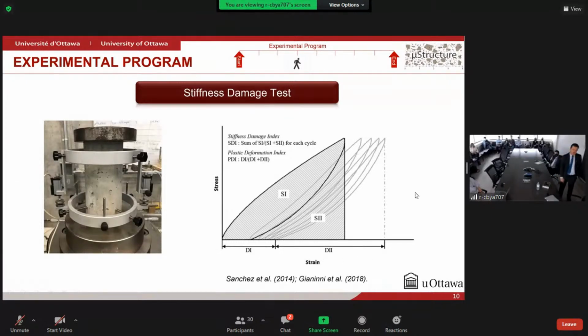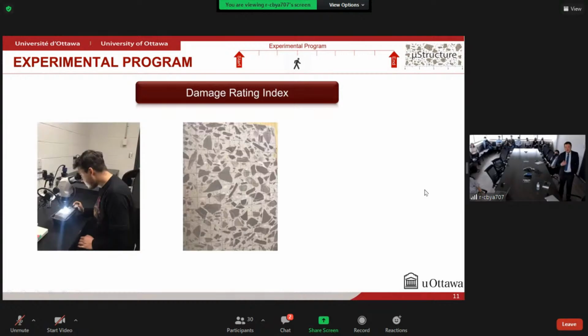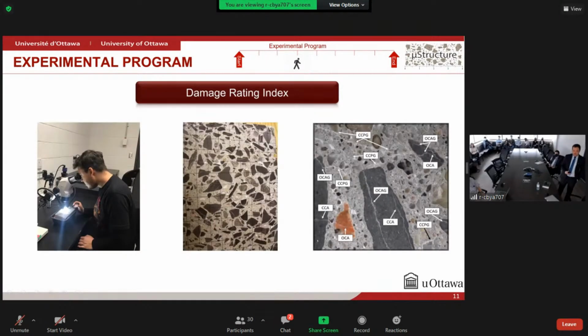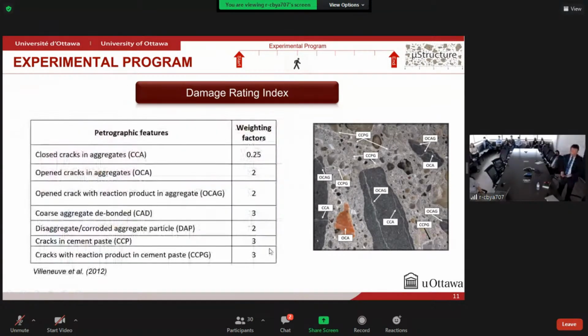As a microscopic evaluation, we use the damage rating index, in which we count the total amount and the different types of cracks per centimeter square of a polished surface of concrete. And with this technique, we can have the extent of damage in concrete. For example, here we have different features for cracks, and for each of them, we have a weighting factor to give a different importance for the cracks, which is based on the development of damage in concrete.